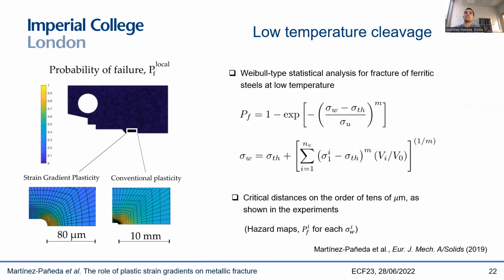Another interesting case is low temperature cleavage. And what we did here is to use a Weibull model, a 3-parameter Weibull model, and calibrate those materials with a classic European steel project where they had measures of probability of failure, where you can calibrate the probability of failure for different temperatures. And essentially, at the end of the day, a Weibull model is a fitting exercise. So we basically were able to see that we get very different values of M and the threshold and all the parameters involved in the Weibull model.